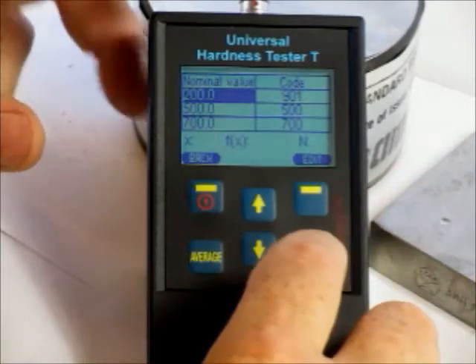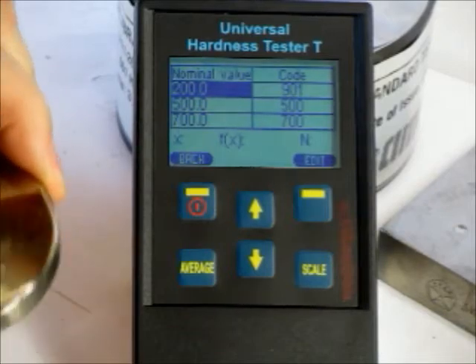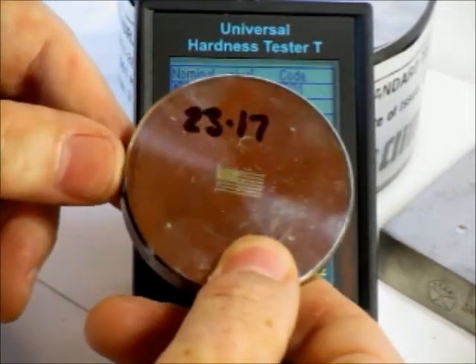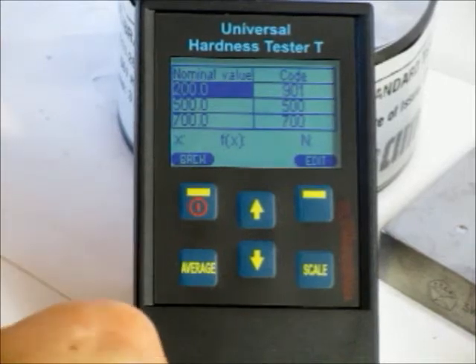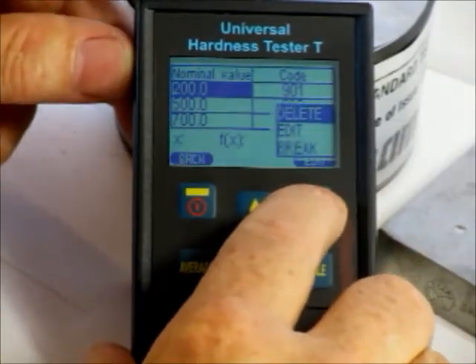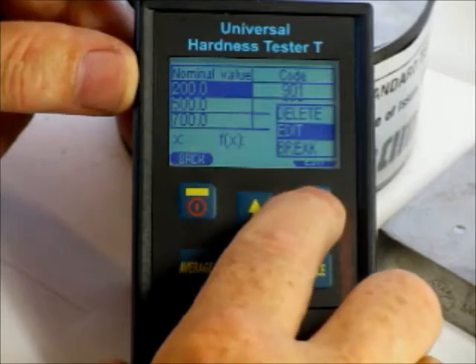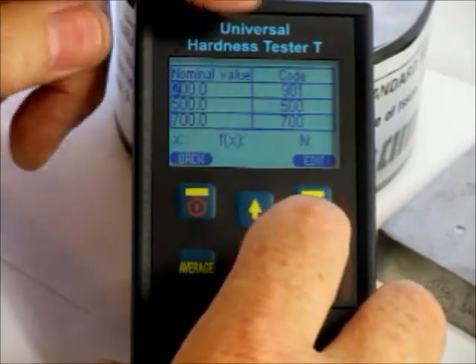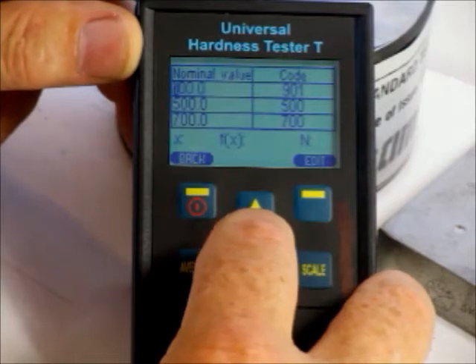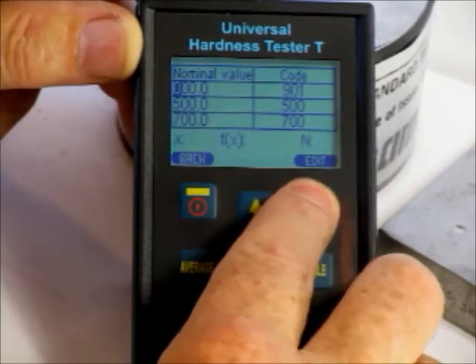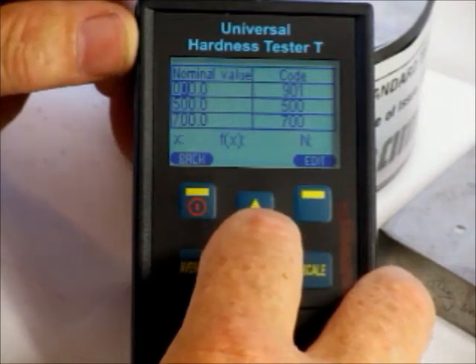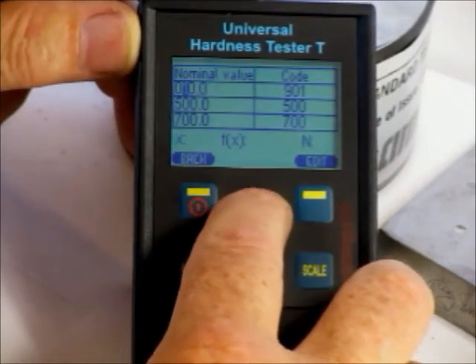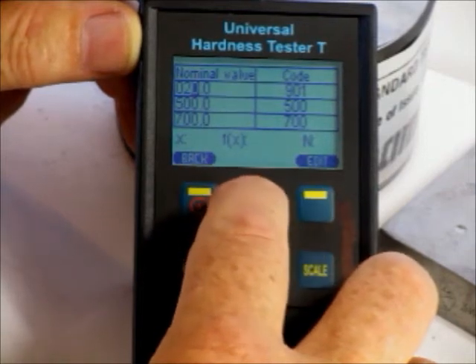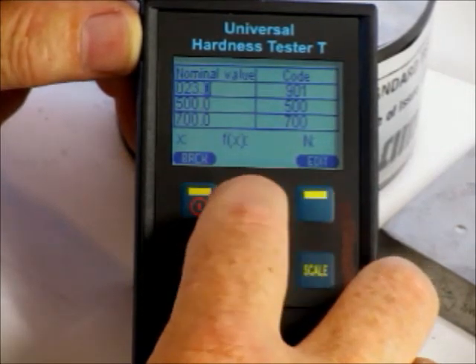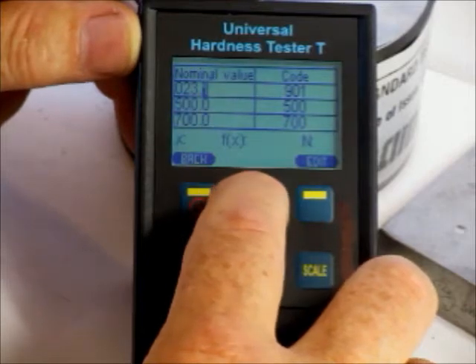And now what I need to do, you can see the nominal value is showing 200. I need to change the value to whatever the test block is. And you can see the test block here is 23.17. So I need to come into this, hit edit. And I want to edit this value, so I say edit. And the display with the background clears off. I want this value to be 1, so I just go down to 1, hit edit, jumps across to the next value. I'm going to put in 23, 2, edit, 3, edit, and it's 17.